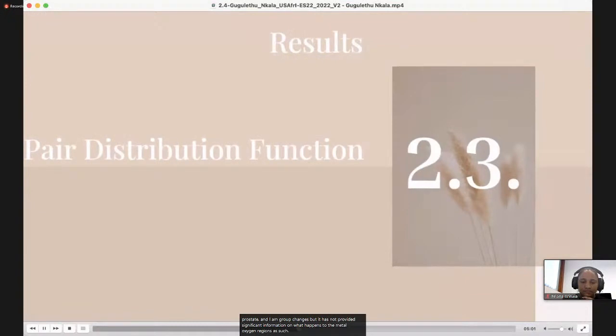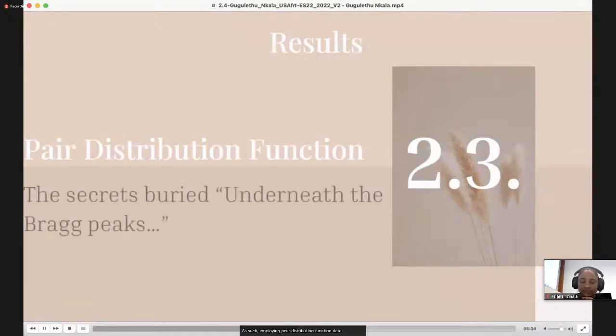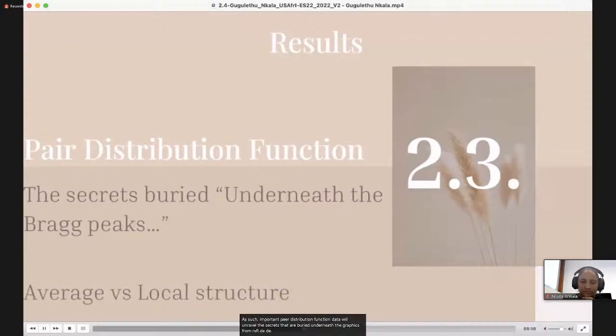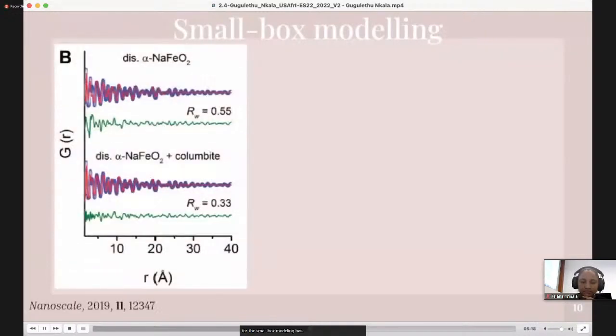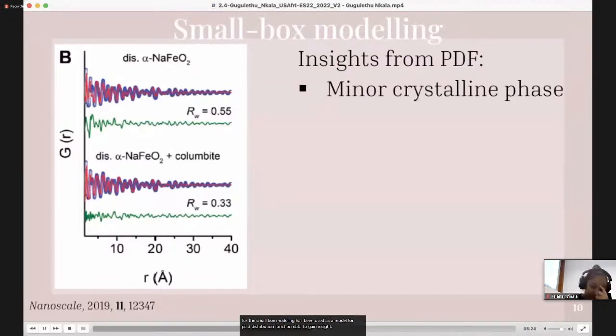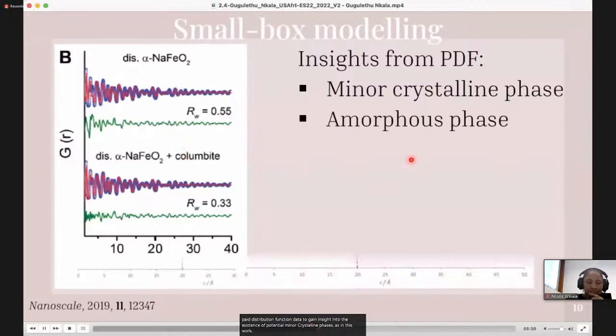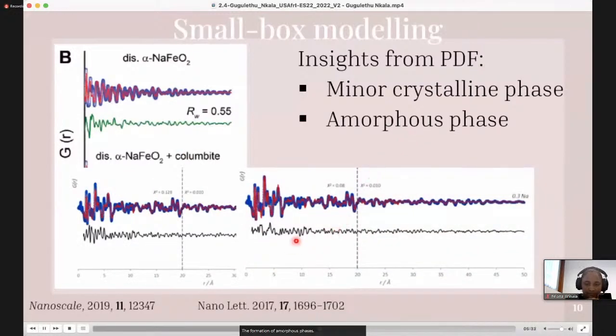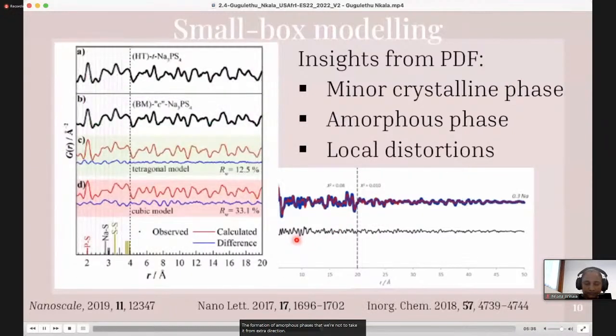As such, employing pair distribution function data will unravel the secrets that were buried underneath the Bragg peaks from our XRD data, to then provide more information on the average and local structure. Small box modeling has been used as a model for pair distribution function data to gain insight into the existence of potential minor crystalline phases, or, as in this work, the formation of amorphous phases that were not detected from X-ray diffraction, or the existence of local distortions wherein the average structure does not agree with the local structure.